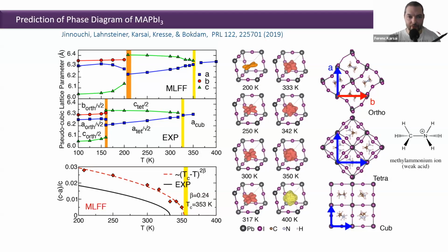But here, the barrier was possibly so low, the structure sizes were large enough, and the time scale was large enough, that we could see these phase transitions occur. The next nice thing is, although they miss the actual experimental values here, the trend is kept. So you see this is more like a right shift of this curve here, and possibly a big reason why this shift happens is, of course, errors in the electron exchange and correlation.